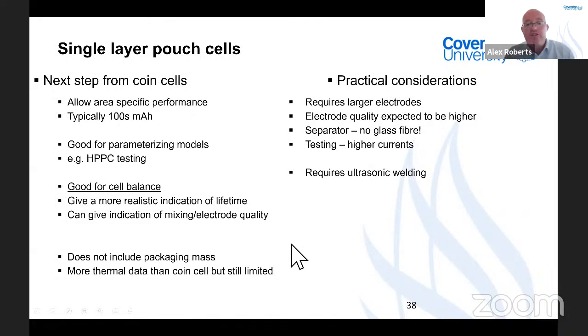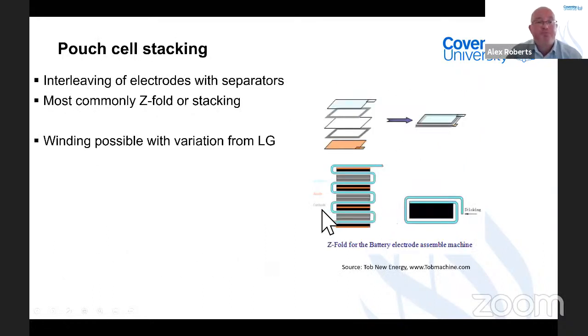There are some considerations if you're looking at these. You need more electrode for this, because it's larger than the coin cell. Also, you benefit from a better quality electrode. And I would say this is the point where you move away from your glass fiber separators. The testing may need higher currents, and often you'll require ultrasonic welding, but there are ways around this, which if anybody would like to contact me afterwards, if you're interested, I could discuss.